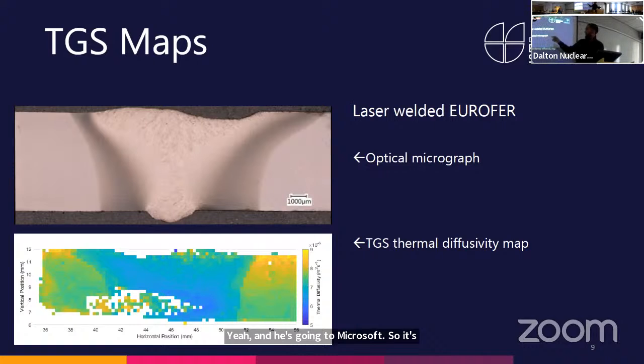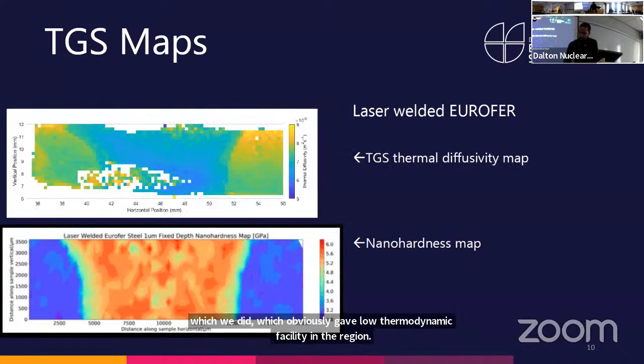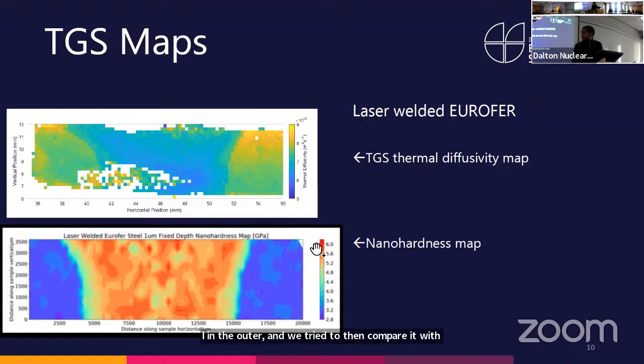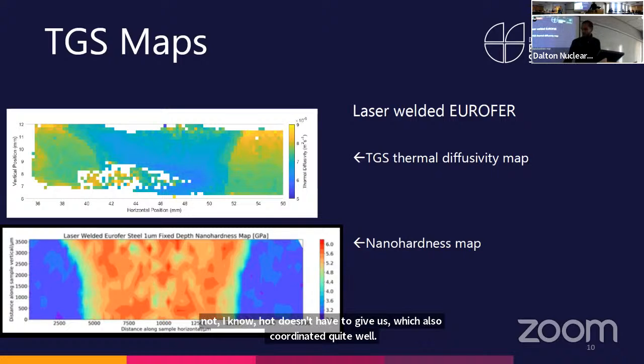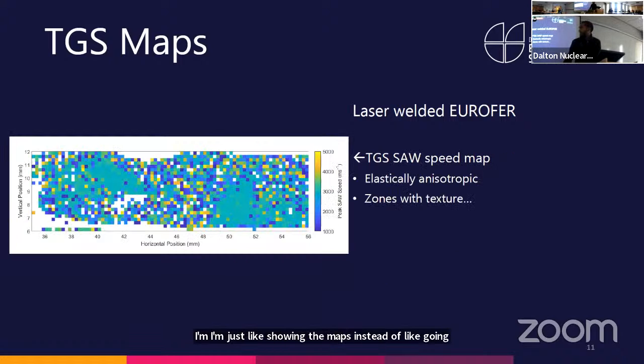So this was a laser welded Eurofer sample. That's obviously an optical micrograph he gave us, and then we did this thermal diffusivity map, which gave low thermal diffusivity in the weld region, higher in the outer, and we tried to compare it with his nano hardness map he gave us, which also correlated quite well. I'm just showing the maps instead of going into a lot of the science bits of it. And this is the surface acoustic wave speed map, but Eurofer is quite anisotropic, so we didn't try to make sense of this.